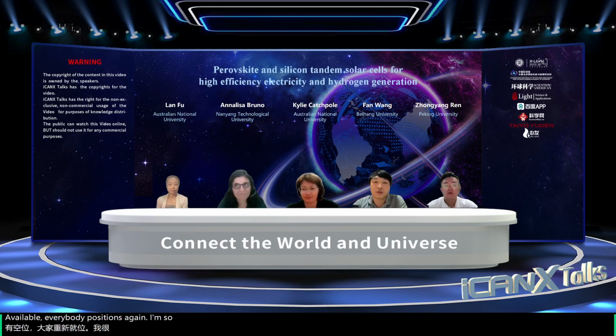So the 86% fill factor was with the titanium oxynitride. That's a different electron transport layer. It was sputtered and then annealed. So we did sputter coating of titanium nitride, and then carefully annealed in oxygen to introduce some oxygen into it. Having that careful control was important.